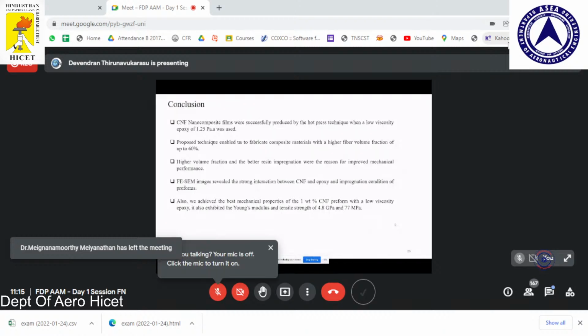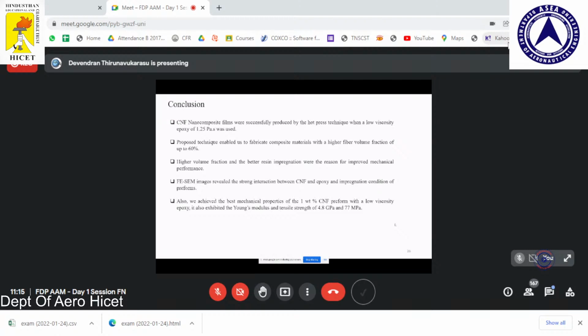In conclusion, the CNF nanocomposite films were successfully produced with the hot press technique using a lower viscosity resin. We achieved around 60% volume fraction. It revealed that 1% CNF preforms with lower viscosity epoxy resins have good mechanical properties. The Young's modulus is 4.8 GPa and the tensile strength is 77 MPa. Yeah, that's all. Thank you for this opportunity.